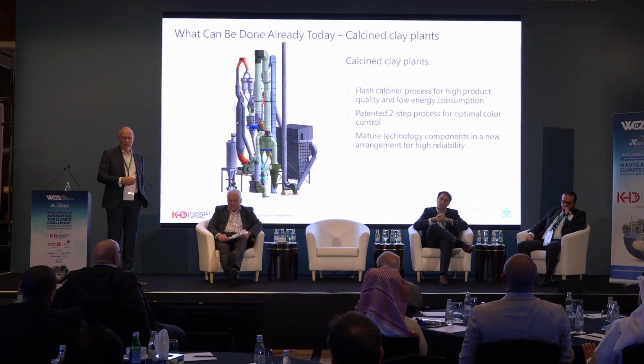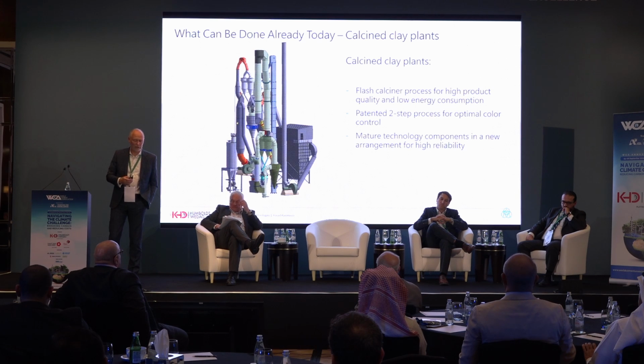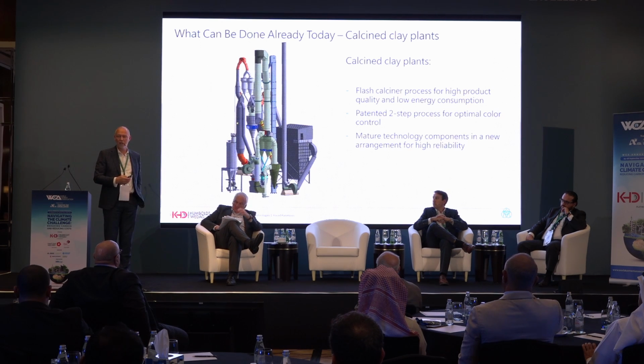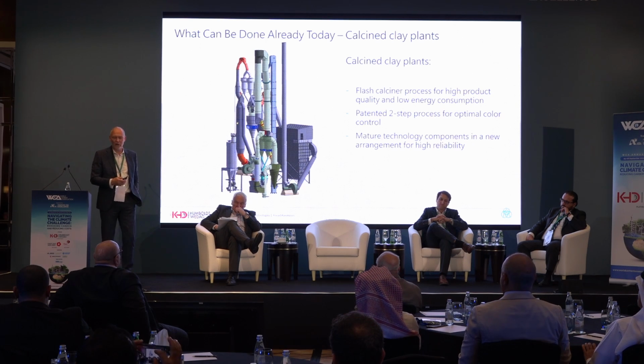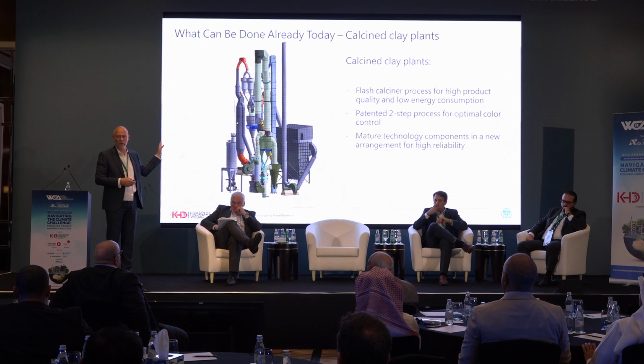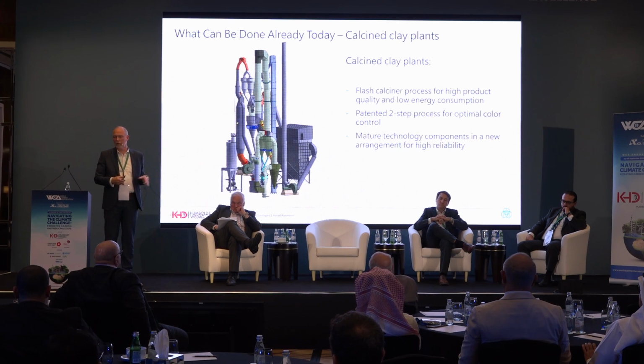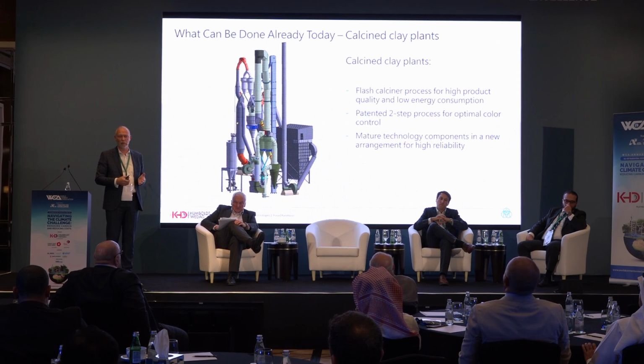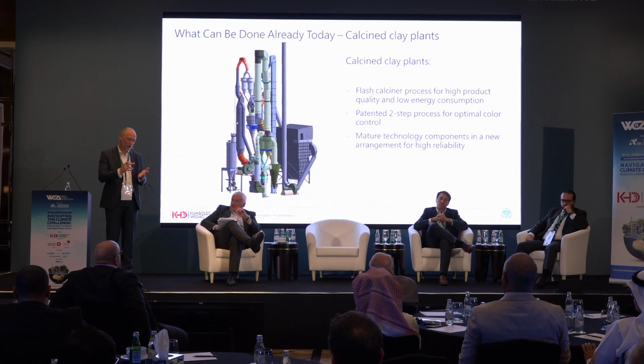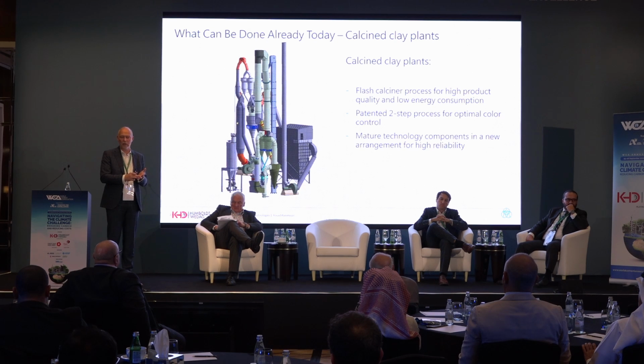Calcined clay. We've also been talking about that, and believe it or not, I recently found out that KHD had the first patent filed back in 1982 on a flash calciner-based clay calciner technology, looking actually like what we're proposing and offering and installing today. So that is a system. We prefer the flash calciner against the rotary kiln for a very simple reason. The quality of the calcined clay depends on the exposure to heat, which is defined by the retention time and the temperature. And if you overrun the exposure to heat, then this calcined clay forms a mineral called mullite, and that is no longer hydraulic active. You don't want to do that.